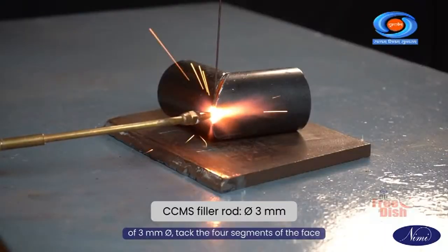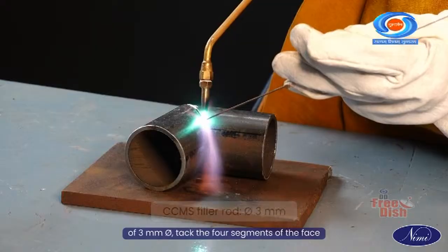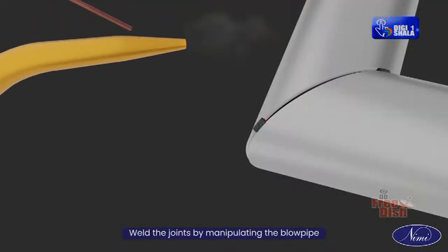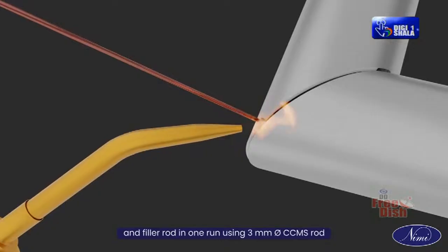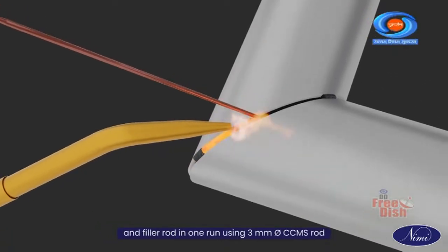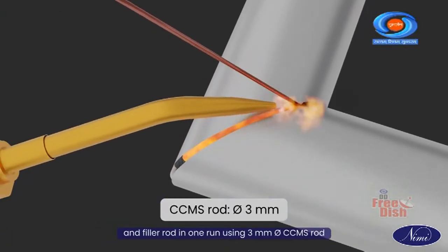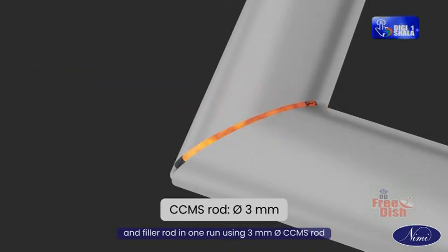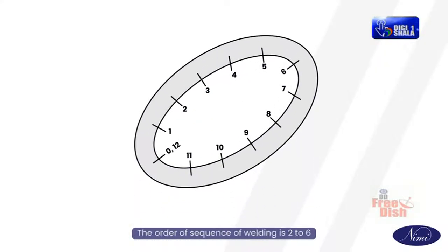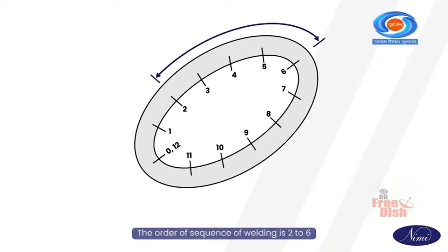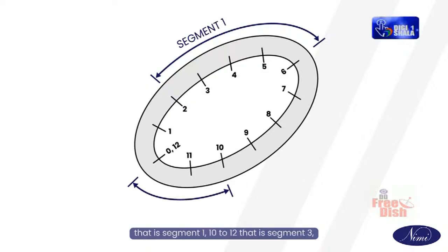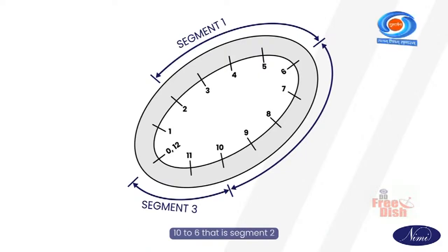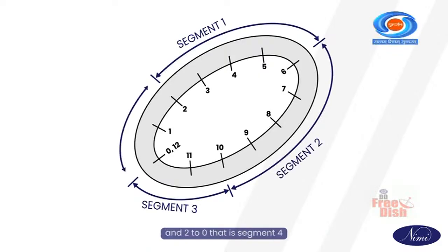Tack the 4 segments of the face. Weld the joints by manipulating the blowpipe and filler rod in one run using 3 mm diameter CCMS rod. The order of sequence of welding is 2 to 6, that is segment 1, 10 to 12, that is segment 3, 10 to 6, that is segment 2, and 2 to 0, that is segment 4.